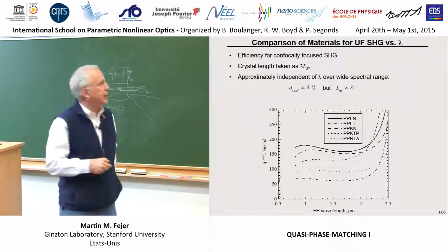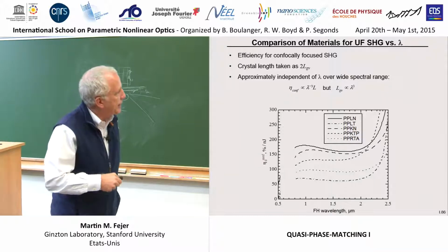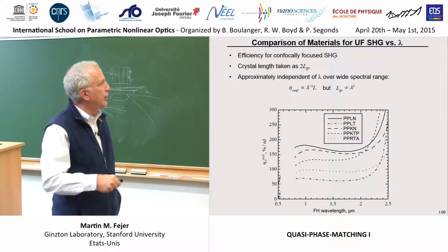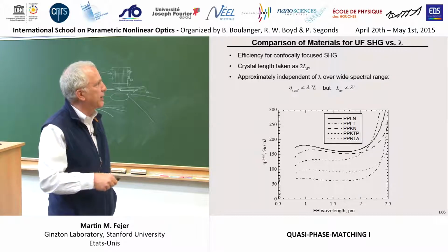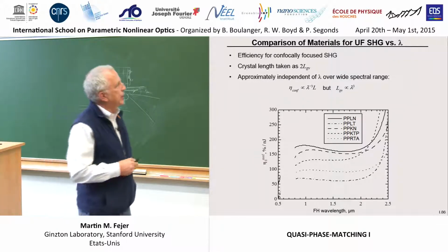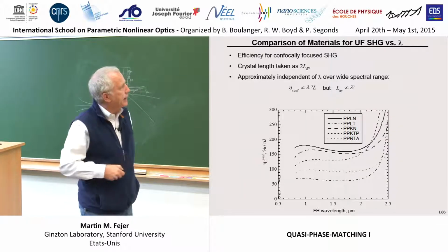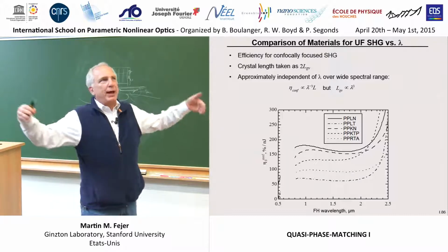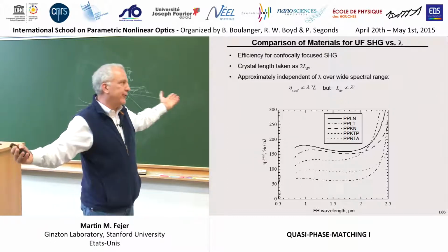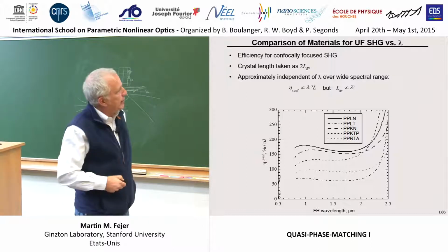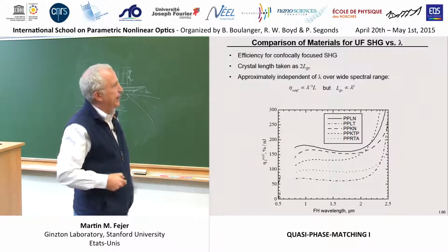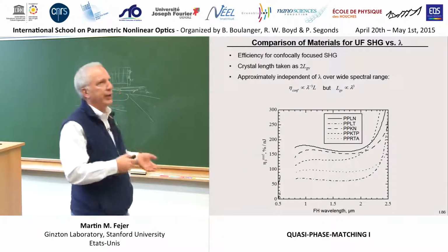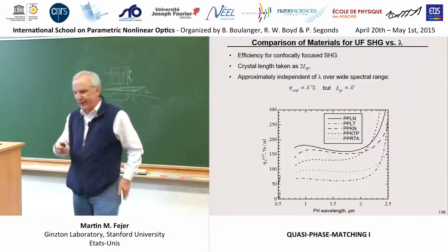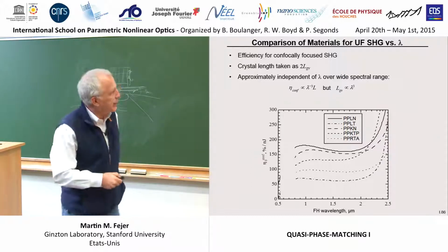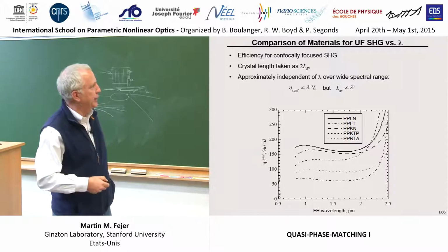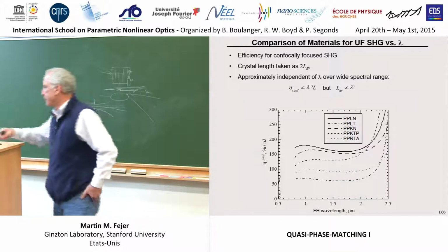It's also interesting that this efficiency is nearly independent of wavelength over much of the transparency range for all of these common materials, which basically is due to the fact that the group velocity mismatch is getting worse with the cube of the wavelength for typical dispersion behavior, but the mixing efficiency is getting better with the cube of the wavelength because there's an omega cubed in confocal SHG. And when you're all done, it's almost flat and in the range of 100% per nanojoule.